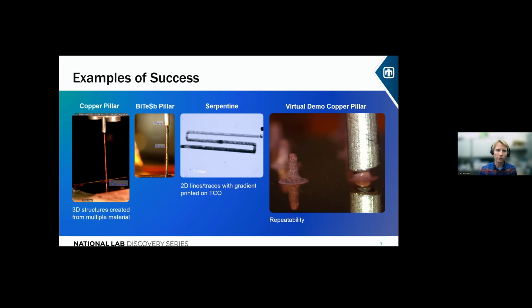The middle is a serpentine type structure, so 2D serpentine, and what you're seeing is a gradient of thermoelectric material that was printed across using a different print speed here, or voltage or power that was applied to deposit the thermoelectric material. So a range of different ways that you control thickness of the material you're putting down. So a number of parameters that can be tuned in to produce materials or structures that might be desired.